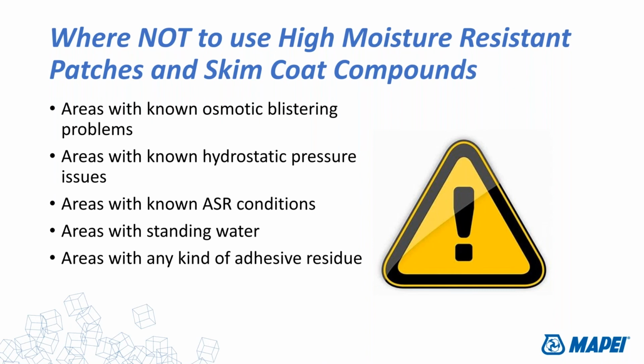And I'm going to caution you to avoid the use of these high moisture resistant skim coats and patches over old adhesive residue of any kind. The reason I'm urging this caution is that you're dealing with a very moist environment, and the sandwich that needs to be made here relies on a great bond between the substrate material, the adhesive material, and the substrate. If you have some sort of ooey gooey adhesive residue on that concrete slab and you're still trying to make it work, that's going to become your weakest link. It needs to be removed, abraded, ground off, to get to a clean concrete if you're dealing with high moisture conditions.